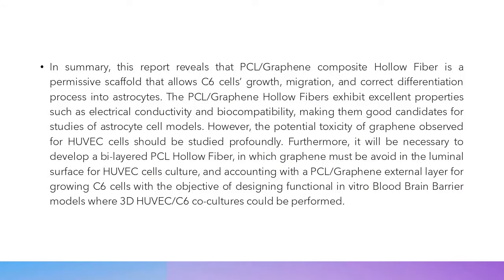In summary, this report reveals that PCL graphene composite hollow fiber is a permissive scaffold that allows C6 cell growth, migration, and correct differentiation process into astrocytes. The PCL graphene hollow fibers exhibit excellent properties such as electrical conductivity and biocompatibility, making them good candidates for studies of astrocyte cell models. However, the potential toxicity of graphene observed for HUVEC cells should be studied profoundly.